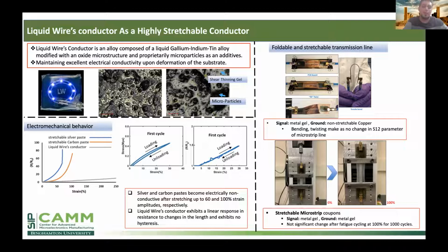If you look at the graph, you can see the comparison between the liquid metal and stretchable silver and carbon paste. Neither the silver nor the carbon one is going to survive more than 100%. For the stretchable liquid metal conductor, even at 250% strain amplitude, the relative change in resistance is just about 10 times the initial resistance. We don't see any hysteresis in resistance versus strain. The hysteresis that you see is for the substrate, which is a polymer, TPU, and that's normal.